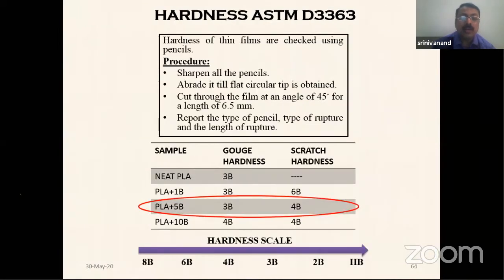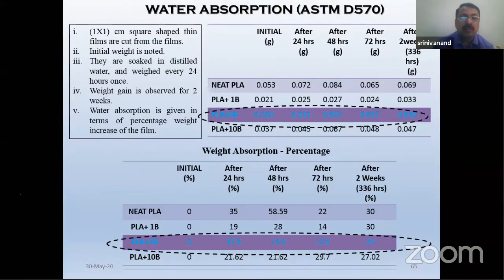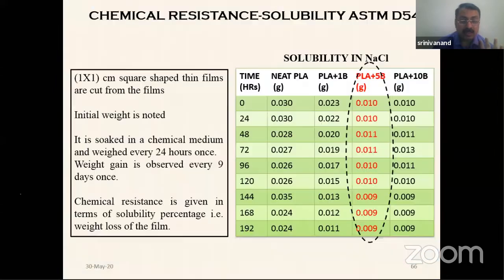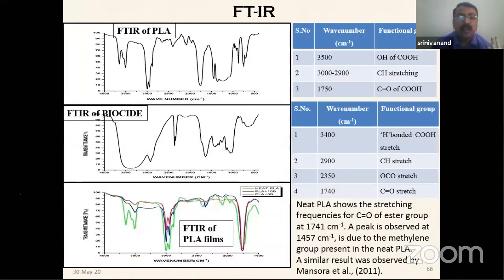Then we did hardness tests and the water absorption test. In all the cases, the PLA with 5% biocide is able to offer a better set of properties. And then we understand the interaction between the biocide and the PLA.